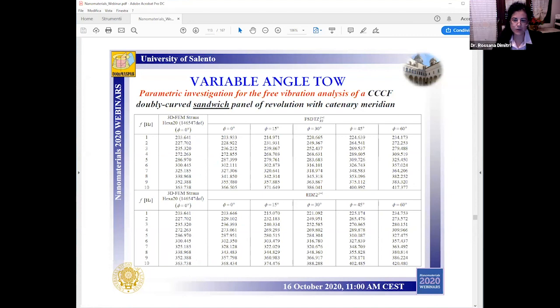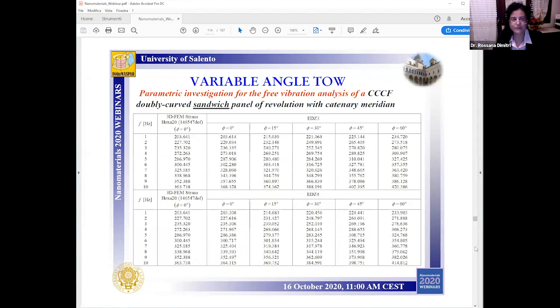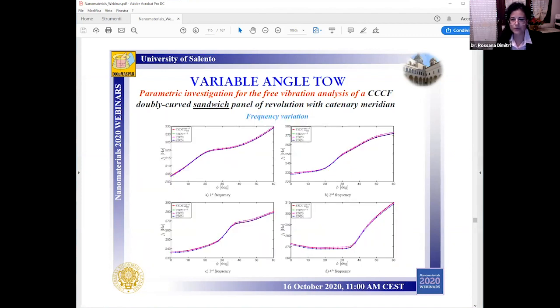So in particular, under the assumption phi equal to 0, the first column here, we revert to classical laminated composite structures, where you can notice the very good agreement between results. Also note that the predictions from different higher order theories are quite close to each other for each fixed value of phi. The same results are also plotted here against phi, just to highlight better the sensitivity of the mechanical response to different distribution paths of the fiber.